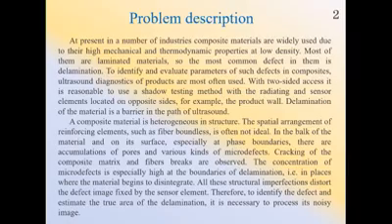Cracking of the composite matrix and fibers breaks are observed. The concentration of micro-defects is especially high at the boundaries of delamination. All this structural imperfection distorts the defect image fixed by the sensor element.